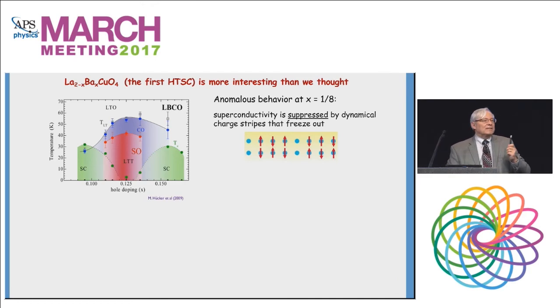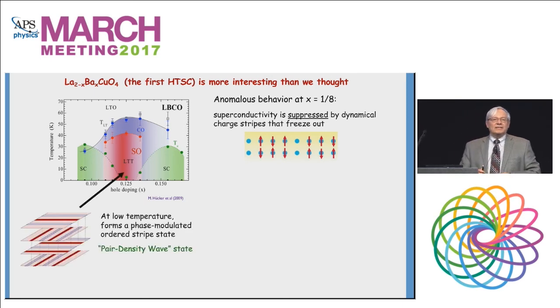We've been looking at LBCO, lanthanum barium copper oxide, the first discovered high-temperature superconductor. Everyone abandoned that because it only had a TC of 30 degrees, but it's in fact more interesting than anyone thought. It has this very precipitous drop in the critical temperature around 1/8 doping. And this is thought to be due to stripe phases in the pseudogap that freeze out. And there's been a proposal for a very exotic state called the pair density wave state by Steve Kivelson and Eduardo Fradkin, which is essentially an ordered stripe phase.